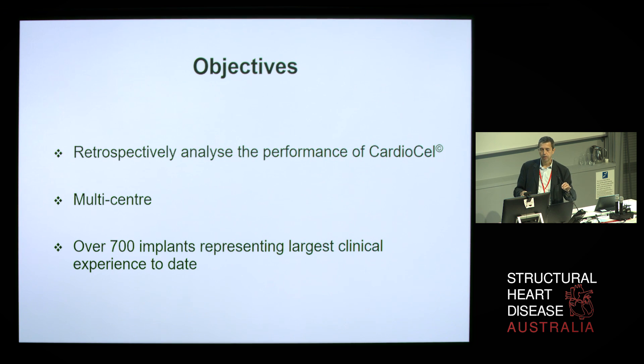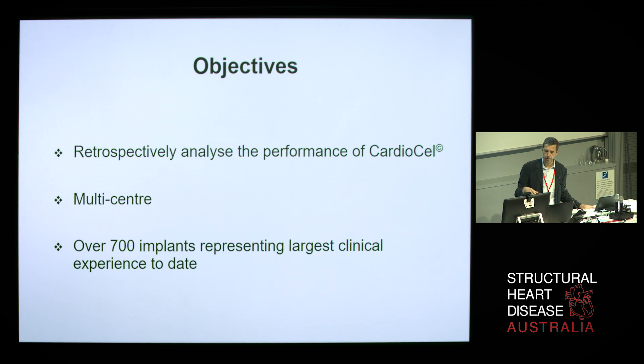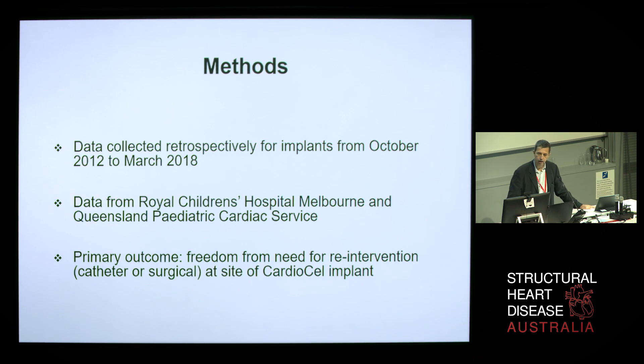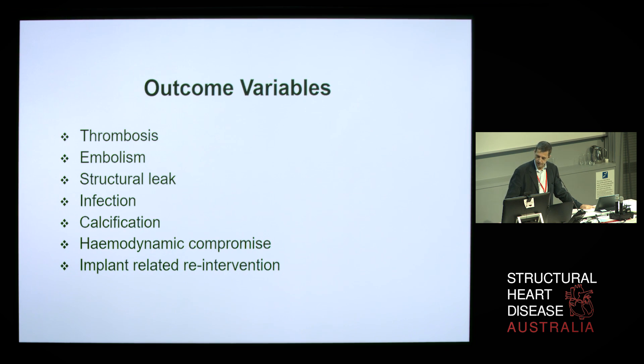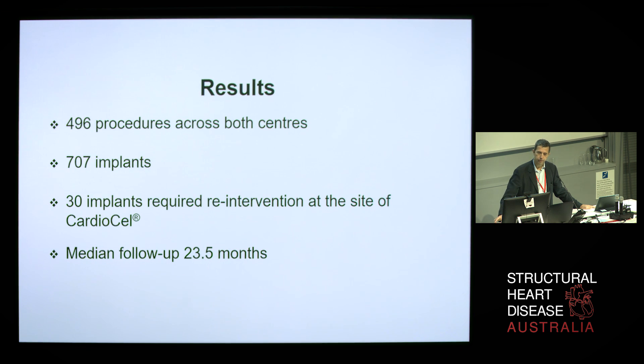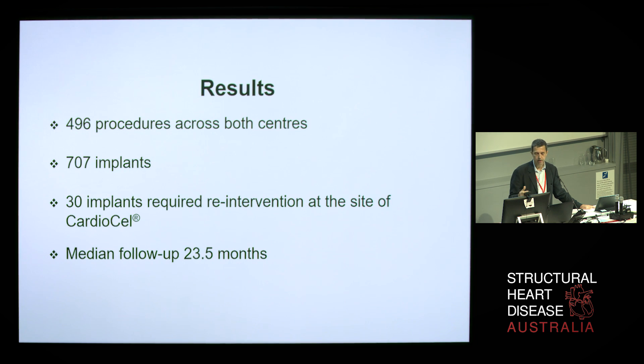We have collected data from the two centers that mostly use CardioCel — the Pediatric Center in Brisbane and the Pediatric Center in Melbourne — about 700 implants between 2012, when it first became available, and March 2018. The outcome variables are collected across almost 500 procedures, with 30 implants requiring re-intervention at the site of CardioCel. Most importantly, as a take-home message: unless it is a neonate in the pulmonary artery branches, it works extremely well.